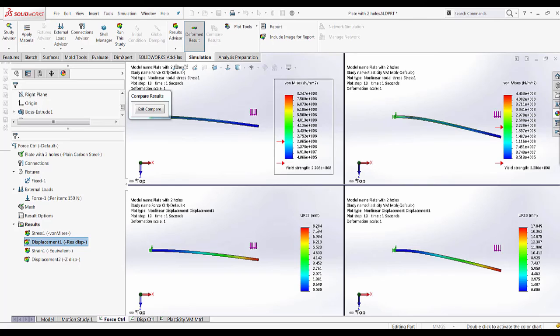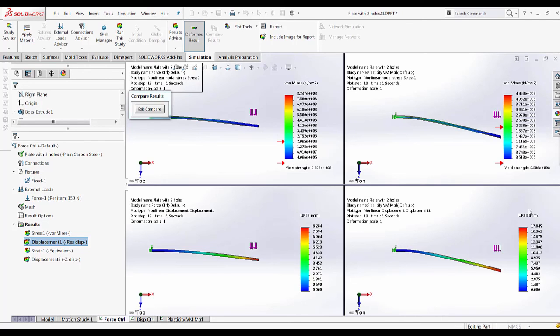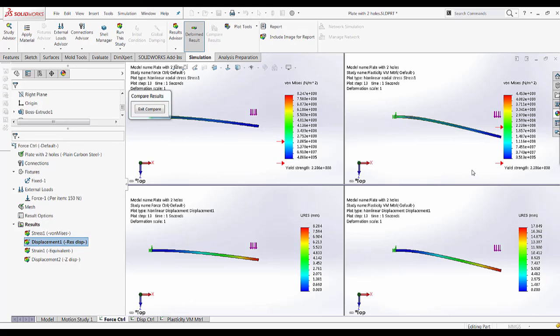The reason for this is when you have a tangential modulus that is much less than the elastic modulus, for the same amount of strain there is not as much stress. But because you have a much smaller modulus number there is a lot more displacement for a smaller amount of force. Hence you see higher displacements but lower stress which is going to be more accurate for modeling material behavior for stresses that are in the plastic region as compared to just using a linear elastic material.